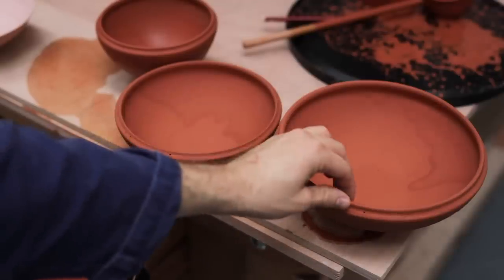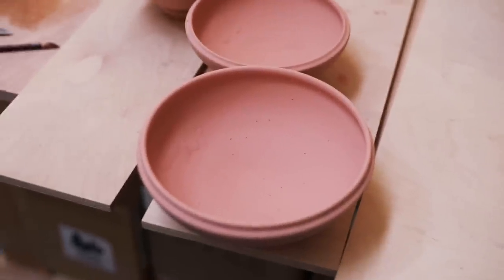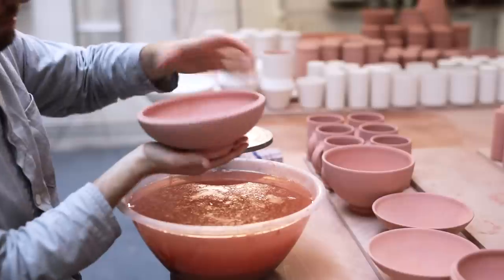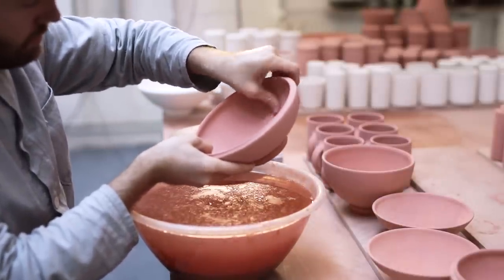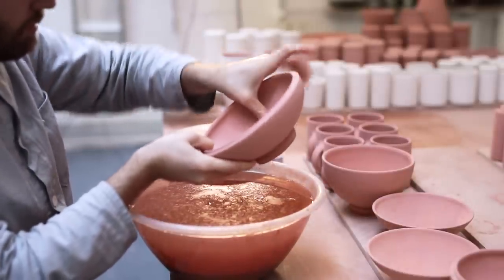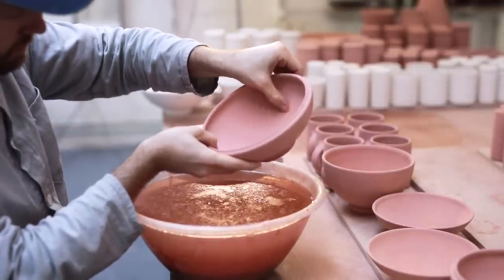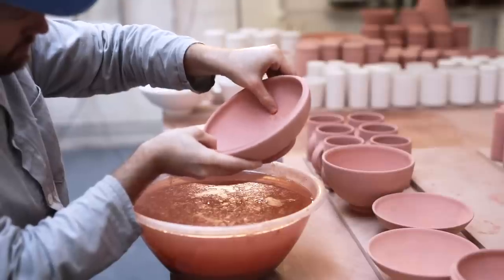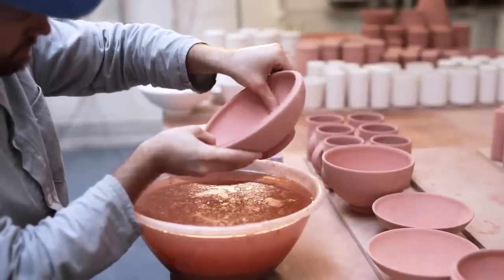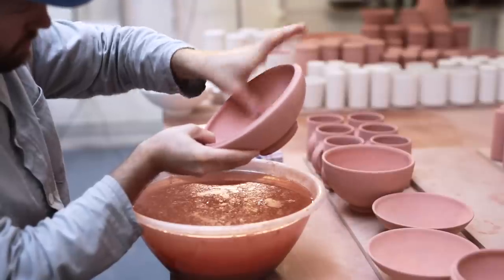And here are the same bowls the following day, only now all that water that was absorbed into the porous clay body has evaporated, leaving a surface that's far more powdery and easier to tidy up. Although it's really worth bearing in mind that if the glazes you're using contain more clay, they'll probably be more stubborn, whereas with this particular glaze, I can simply rub the tips of my fingers over any thick points to gradually wear them down, such as the marks left by the tongs.